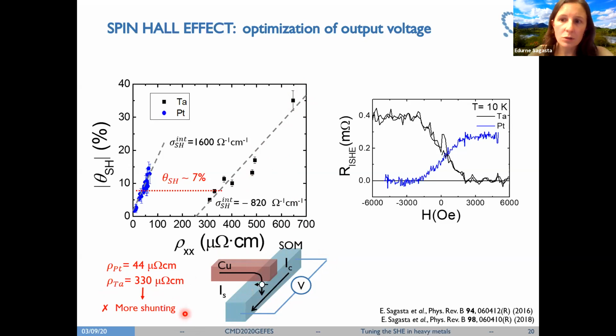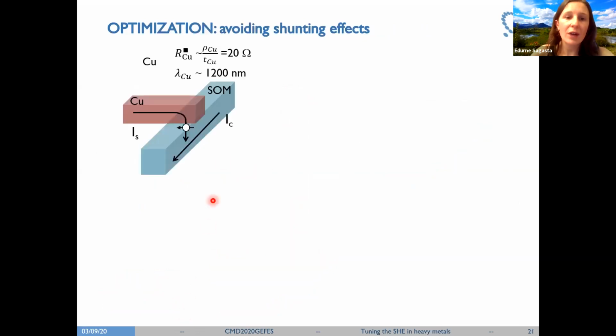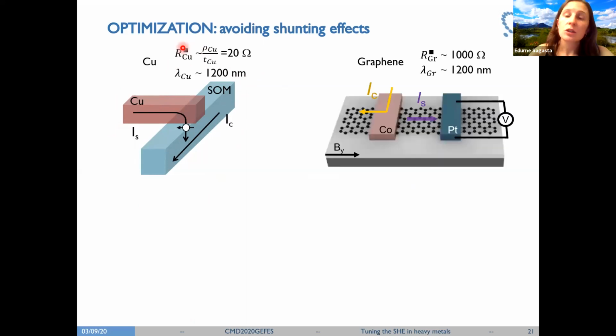So our approach was, instead of modifying the spin orbit metal, why don't we substitute the copper by a more resistive material so that we can overcome the shunting effect? So this is why we decided to use graphene, because it's characterized by a long spin diffusion length, as long as copper. In fact, in the case of graphene, it is constant with temperature, and in the case of copper, it decreases with temperature. So this factor we have in favor.